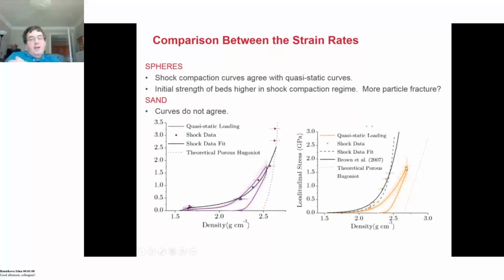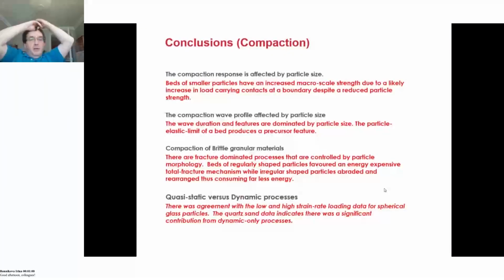Again, I think it's to do with the range of particle fracture times in the system. So the conclusions here in the compaction is the compaction response is affected by particle size. Beds of smaller materials have an increased macroscale strength due to the number of load carrying contacts at the boundary. The compaction wave is affected by particle size. The duration and the features you see are quite clearly marked. So the particle elastic limit, so the fact that the spheres have some initial strength, produces a precursor feature.